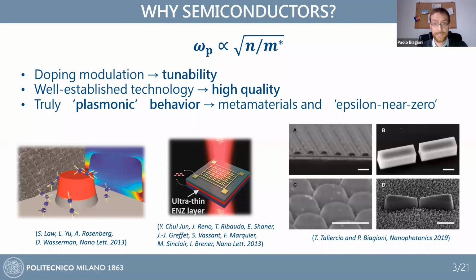higher losses in terms of scattering rates, but you also have, for a given working frequency, a lower penetration of the fields in the volume of your plasmonic antenna. So it's true that the volume losses increase, but it's also true that the fields do not penetrate the volume so much anymore. And indeed, if one wants to take a figure of merit for losses, it has been discussed in the literature. There are a couple of nice papers, one by Jacob Khurgin, for example,